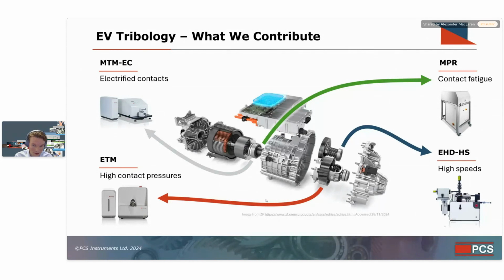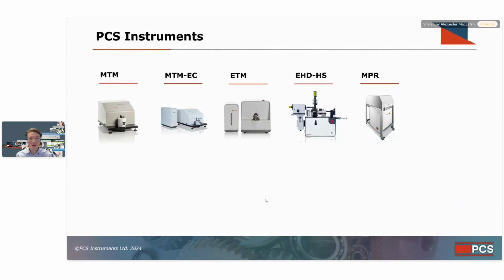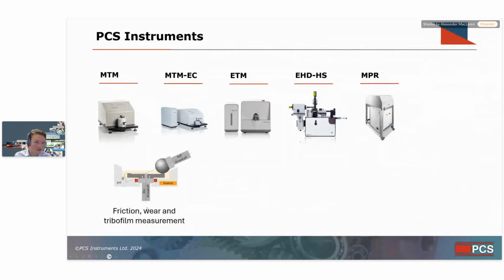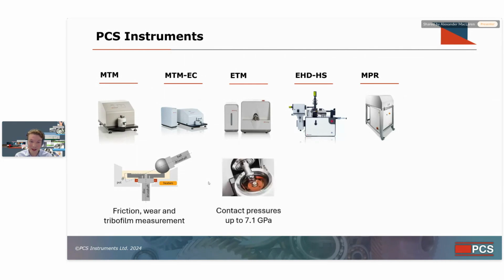And so I'll just highlight a couple of these, and then I'll tell you a bit more about what PCS are up to at the moment, some exciting things in the pipeline, and also how we engage more widely with the community. So the MTM and MTM-EC, so that's mini traction machine electrical contact, or electrified contact, are just ball on disc tribometers. The ball and the disc are driven independently, and so you can achieve an arbitrary entrainment speed and slide roll ratio combination. They're loaded against each other to simulate really a bearing, the contact in a bearing. And this was one of the first machines that was able to measure friction in a single contact using materials and conditions that represented a bearing well. And so it's been instrumental in the development of lubricants and the understanding of lubrication phenomena for several decades.